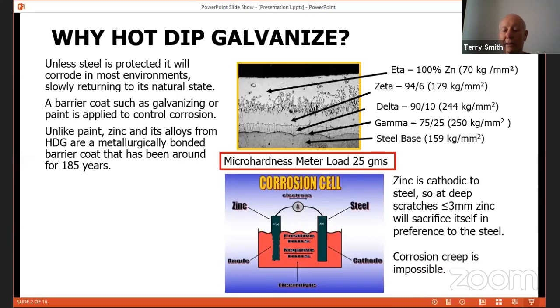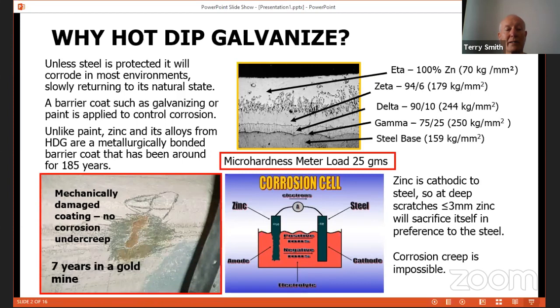Corrosion creep is also impossible with hot-dip galvanizing. Here's some mechanical damage to the coating after 7 years in a gold mine on some shaft guides, and you can see there's no corrosion creep at all.